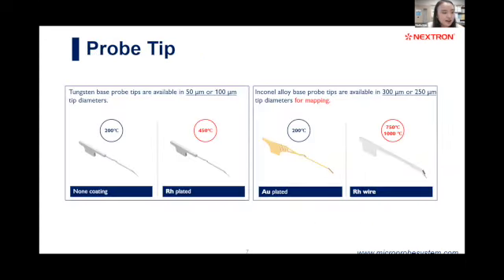Turn to the next page. There are several kinds of probe tips we have. First, tungsten-based probes in 50 micron or 100 micron size. Depending on the operating temperature, a rhodium coating will be applied to avoid oxidation issues. We also have relatively bigger probe tips: Inconel alloy tip in 300 micron, rhodium wire tip in 250 microns. The bigger the probe tip is, the more durable it is and the stronger its ability to fix the sample.